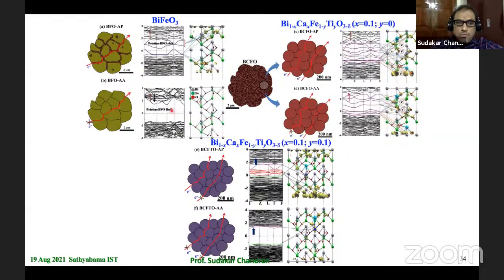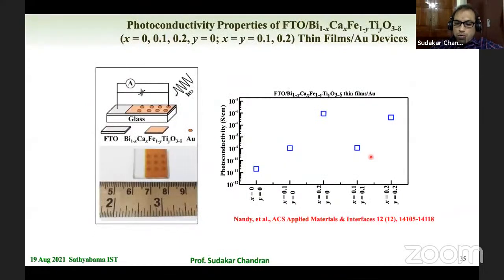Of course, the defect states mostly in the pure bismuth ferrite, there is a large band gap, anywhere from 2.4 to 2.8 eV, which is consistent with what we find from the experiment. But in the case of samples that have surface defects, you do have energy levels corresponding to the oxygen vacancies from the surface region or due to the dopants, and depending on the concentration, they can make separate energy bands, and therefore the optical properties do change, and the band gap does change. These oxygen vacancies are known to play a significant role in controlling the photoconductivity properties.